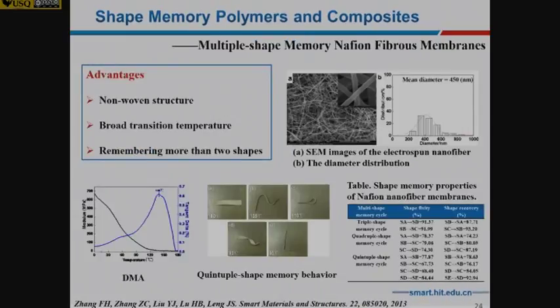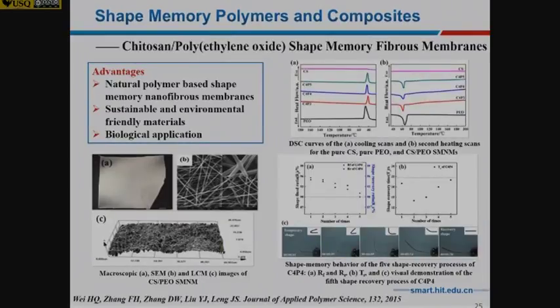So let me take some examples. This is one we made by electrospinning. This is also a multi-shape shape memory polymer membrane. You can see from 160 degrees, 135, 110, they have a different shape, which means this one can remember 3 different shapes. So we also made some biocompatible shape memory polymer, which we call chitosan, and also made a membrane for the scaffold for applications.